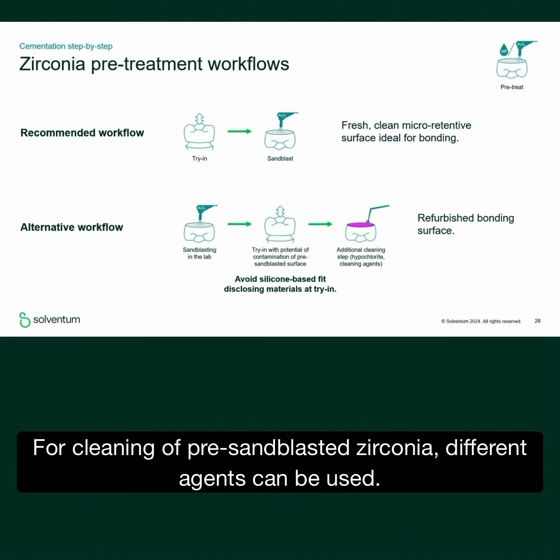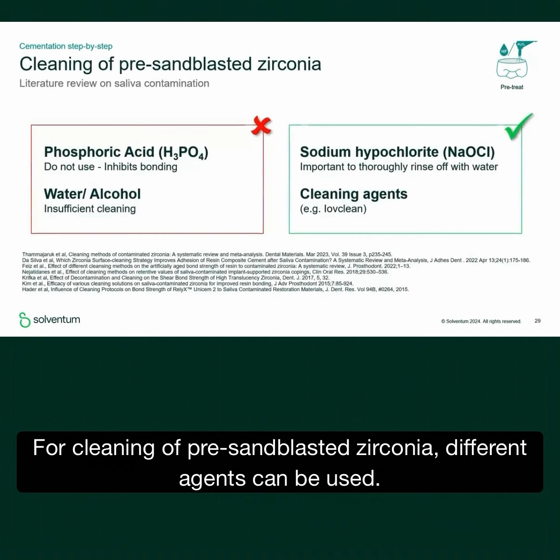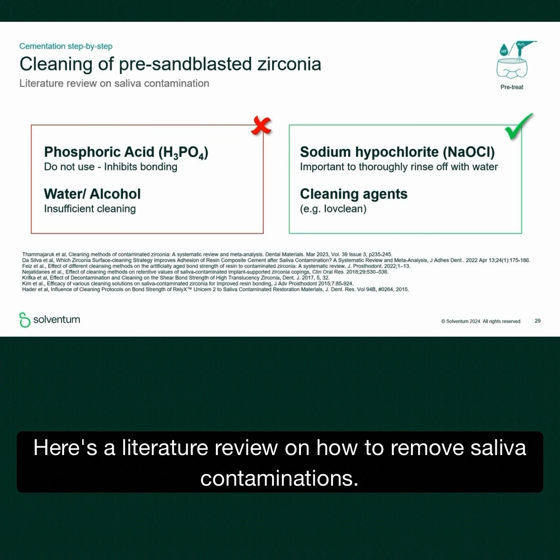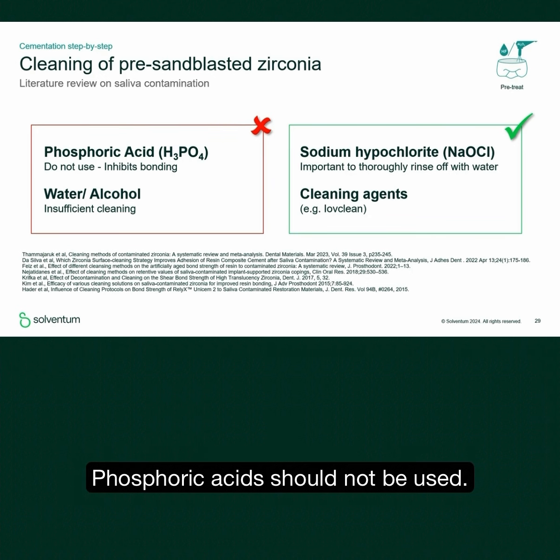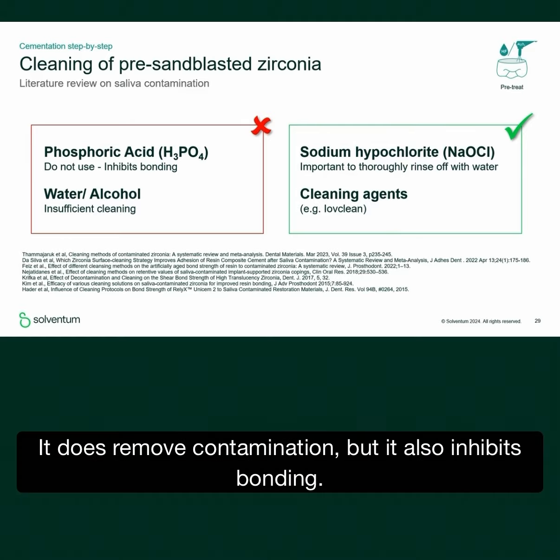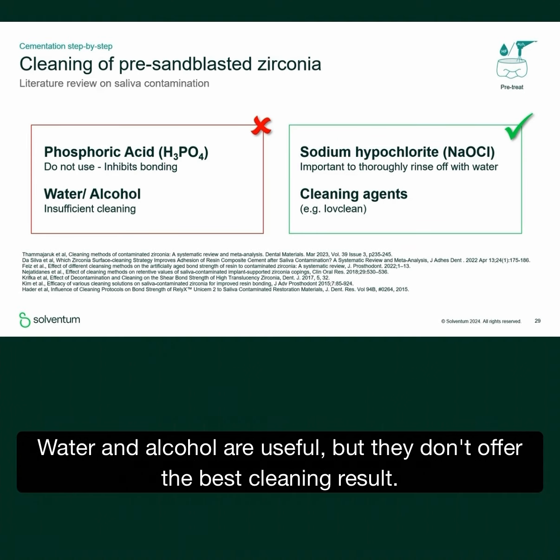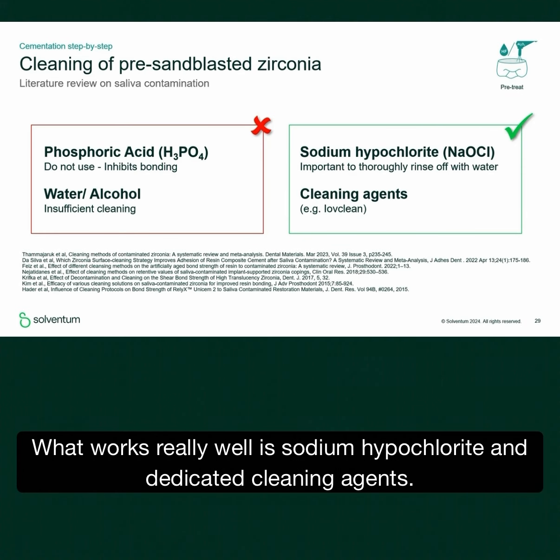For cleaning of pre-sandblasted zirconia, different agents can be used. Here's a literature review on how to remove saliva contaminations. Phosphoric acid should not be used. It does remove contamination, but it also inhibits bonding. Water and alcohol are useful, but they don't offer the best cleaning result. What works really well is sodium hypochlorite and dedicated cleaning agents.